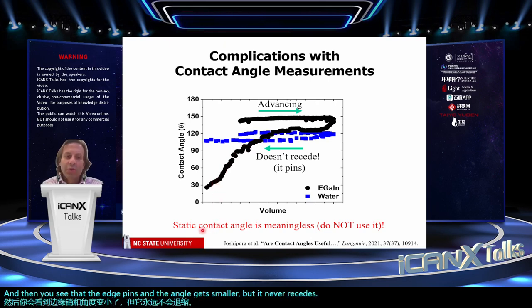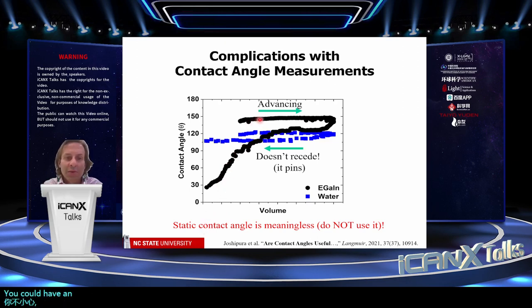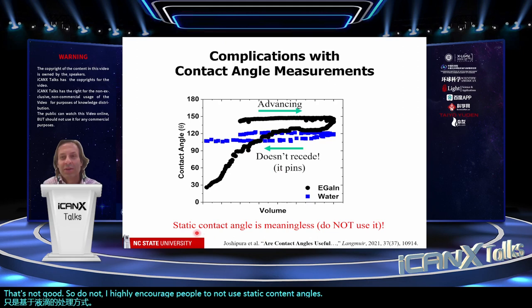So what is the point here? If you just stick a droplet on a surface and you're not careful, you could have an angle that's all the way between 150 degrees down to, I don't know, maybe 20 degrees. So you could go from this all the way to this, just based on the way that the droplet is handled. That's not good. So I highly encourage people to not use static contact angle because it doesn't mean anything. You should be using advancing angles.